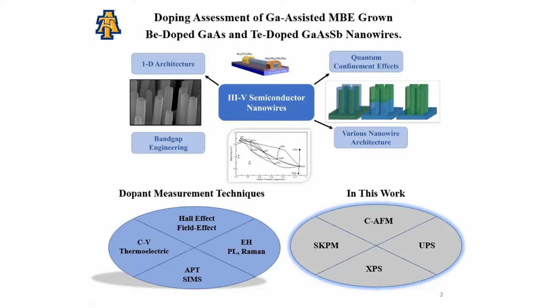Dopant incorporation in a well-controlled manner is essential to produce abrupt interfaces, to modulate work function, and to realize advanced devices in nanowire configuration successfully. Unfortunately, the thin film studies on dopant incorporations and carrier concentration cannot be directly translated to nanowires due to the doping's influence on the growth kinetics and different growth mechanisms along the axial and radial directions.